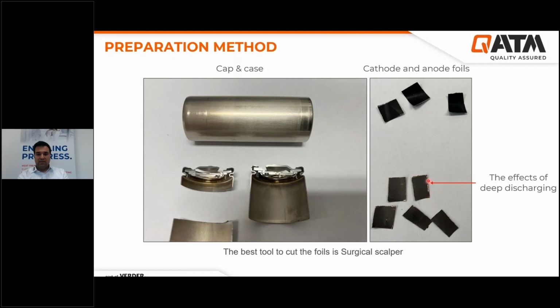Here you can see the effect of deep discharging on the battery, because we use the normal batteries and we deep discharge them, and here you can see the gap between the coating and the copper foil in the anodes. And also in the cathodes you can have some cracks on the metal oxide particles.